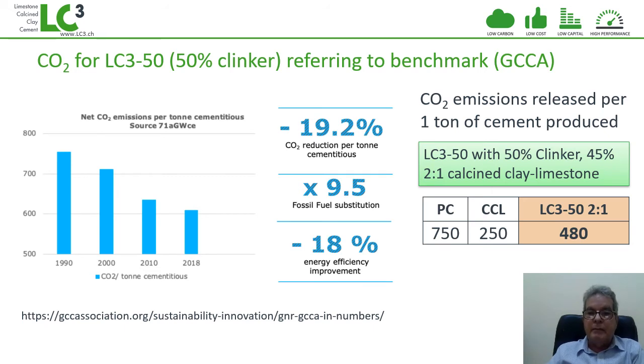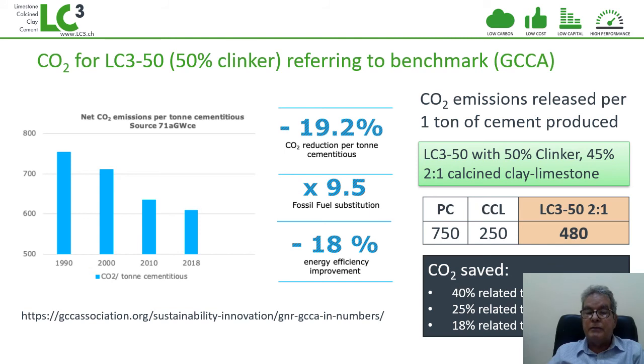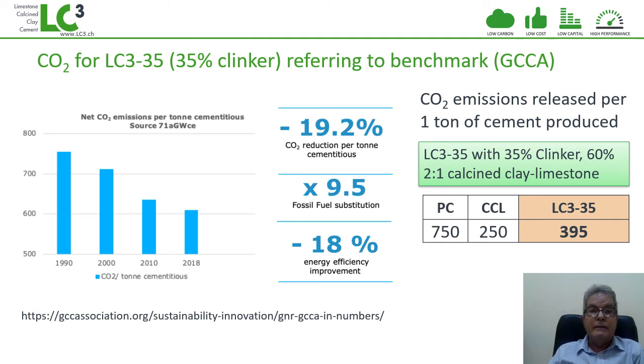Now we are going to compare the impact of these new cements on carbon emissions, how we can reduce them. In the first case we studied, regarding strength, remember we were using 50% clinker, and with this we were able to match the properties of a CEM I 42.5, which has carbon emissions in the range of 750 kilograms per ton. We have calculated in our studies that the blend of calcined clay and limestone more or less emits 250 kilograms of CO2 per ton. And when you put this together, you realize that you have 480 kilograms of CO2 per ton of LC3, which compared to CEM 1 is 40% CO2 savings, but also significant savings compared to other types of cement produced.